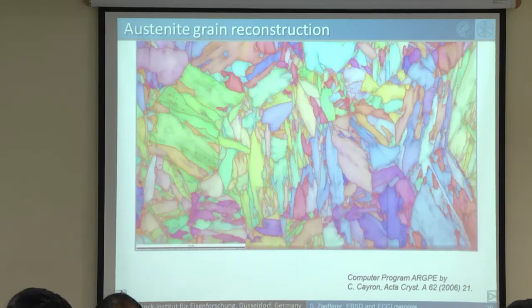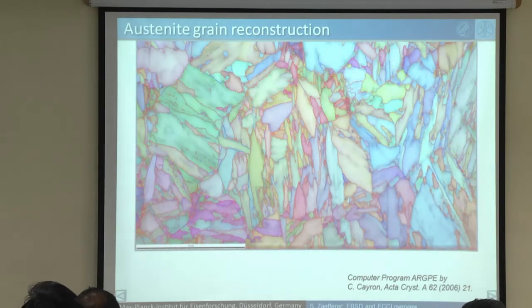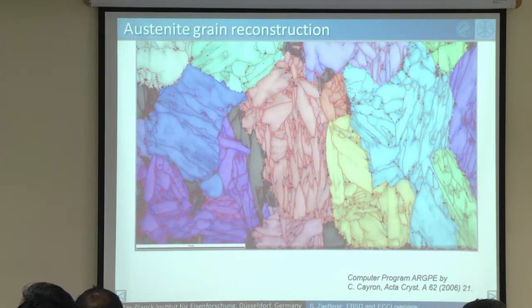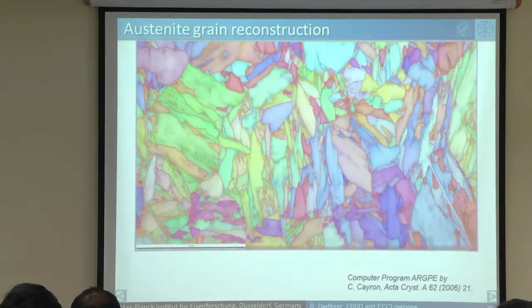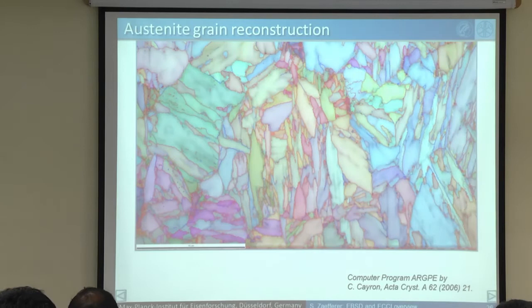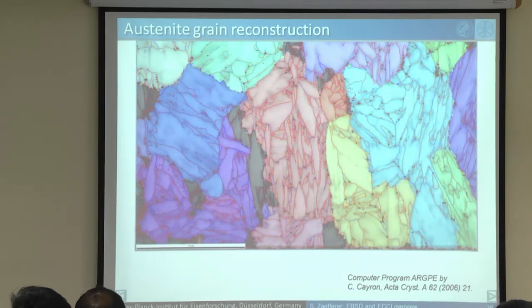of the original austenite. And this is done by another beautiful computer program, ARGPE, created by C. Cayron. And this software just looks through this microstructure and looks for these relationships. And then actually what it does, it finds these. Yeah? And actually it regroups martensite, which all fit to the same austenite. And once again, this was a martensite. You don't see that there are grains inside. Yeah? At least if you have no prior knowledge, you don't see that. But if you now let the software go over it, you find, aha, there's a beautiful reconstruction into different grains.